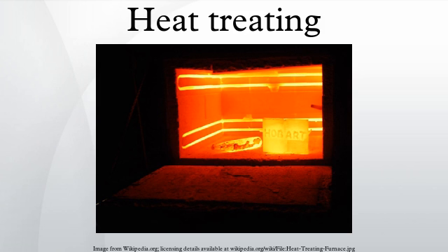At around 350 °F the steel will start to take on a very light, yellowish hue. At 400 °F, the steel will become a noticeable light straw color, and at 440 °F, the color will become dark straw. At 500 °F, steel will turn brown, while at 540 °F it will turn purple. At 590 °F the steel turns a very deep blue, but at 640 °F it becomes a rather light blue.